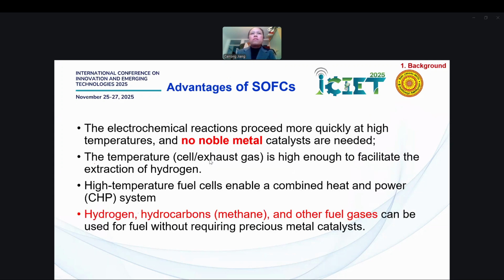There are a lot of advantages I've mentioned a little bit before, but I want to show more on why we choose solid oxide fuel cells. The first thing is that no noble metal is needed, like platinum or gold. We don't need this type of catalyst; maybe some common compounds will be sufficient for the catalytic reaction. The second advantage is that the temperature is high enough to facilitate the extraction of hydrogen. The third advantage is that high temperature fuel cells combine heat and power, so we can go up to 80 to 90% efficiency.